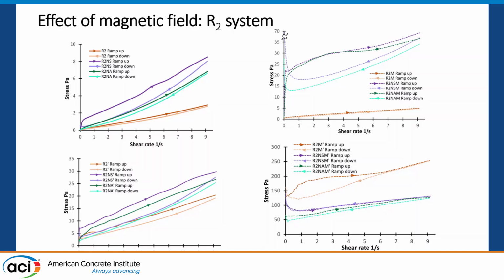Extremely fluid systems can be stiffened significantly by applying a magnetic field, especially systems with magnetite powder. You can see that complete transformation of the reference material with just 45% of fly ash and 5% of magnetite powder. It was Newtonian behavior without magnetic field, and with magnetic field, considerable stiffening is achieved. Again, compatibility between magnetic inclusions and nanomaterials needs to be further investigated.